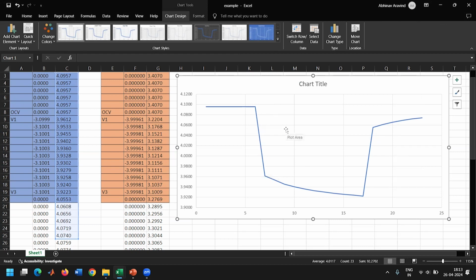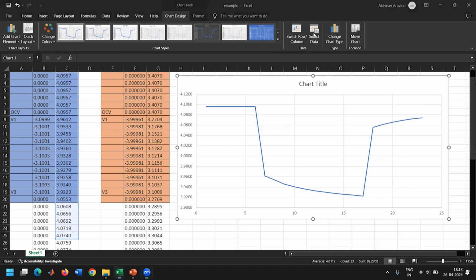So basically, it's the same thing that is repeated at different SOCs. Okay, so if this is at 100%, then you can measure the same voltage response at say 90%, then at 80%, and so on, till the SOC achieves complete 0%. So in the entire SOC range, 100 to 0, you can measure the total ohmic and polarization and also the charge transfer resistance.